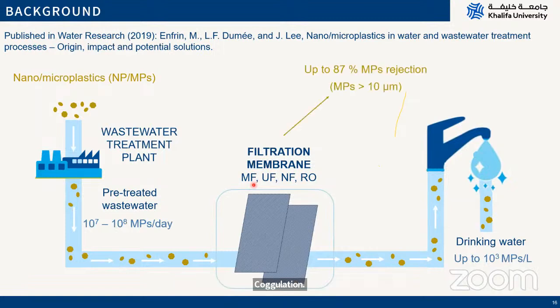But reaching the MF or UF is quite possible, because some of the pretreatment like coagulation, AOPs and so on are not always effective in removing them. And it has been reported that only up to 87%, I guess, of microplastics can be rejected if they are larger than 10 micrometers. But anything below that was not evaluated at all until we did these studies.